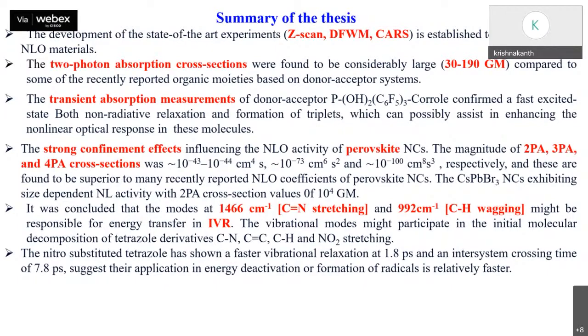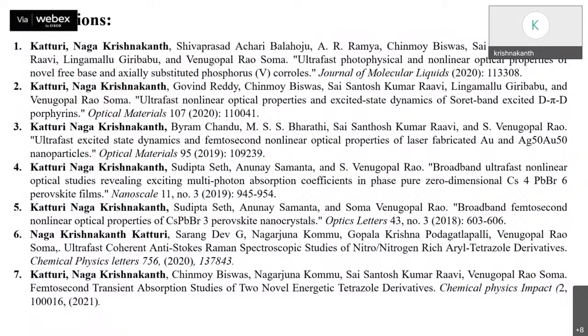And from the CARS experiments on the two tetrazole molecules, we observe that CN stretching and CH wagging are the two bonds which mainly participate in the IVR process, and other bonds like CN, CC and CH tend to decompose very quickly considering their lifetime. The nitro substituted tetrazole has shown faster vibrational relaxation, at 1.8 picoseconds. From the transient absorption studies, we have concluded this, and these are my publications. Thank you.